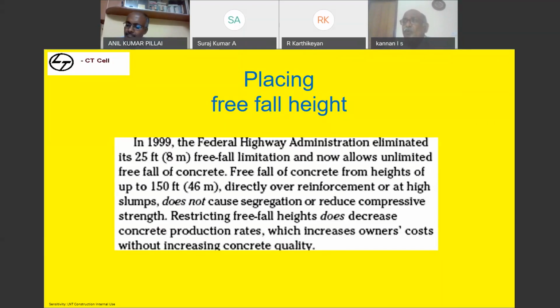So in such cases, what you have to do is, suppose if you are going with the high lift column and all, don't go with the normal slumpable concrete of 100 mm or 120 mm and all. Go with the self-compacting concrete or high flow concrete, where you can design a mix like a piling concrete of around 200 or 220 mm slump, where your flow will be around 400 to 450 millimeter. Use such concrete and do a slight tamping on the top, or you can use a 25 mm needle and compact it so that the segregation can be avoided. Only thing is, depending upon the situation, design a mix and place the concrete so that the structure is safe. The ultimate idea is we have to make a defect-free structure.